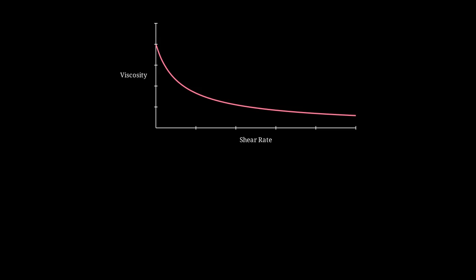As shear rate increases, viscosity decreases dramatically. The faster you stir, the thinner it gets. The mechanism is that jammed droplets get aligned and start sliding past each other in layers when you apply high shear. Under shear, droplets arrange into flowing layers, dramatically reducing resistance compared to their random jammed state.